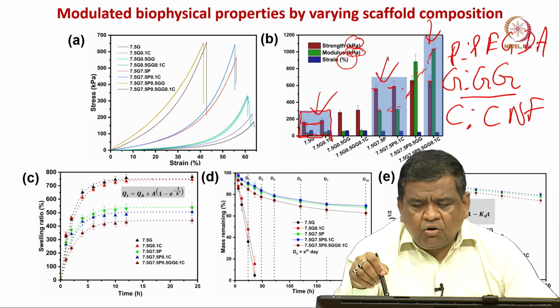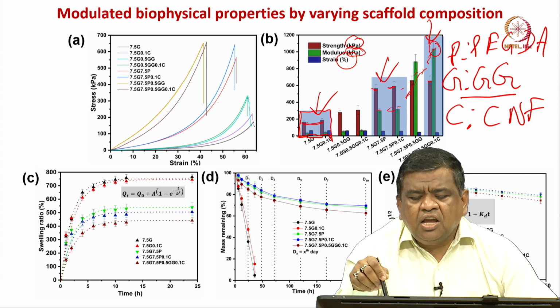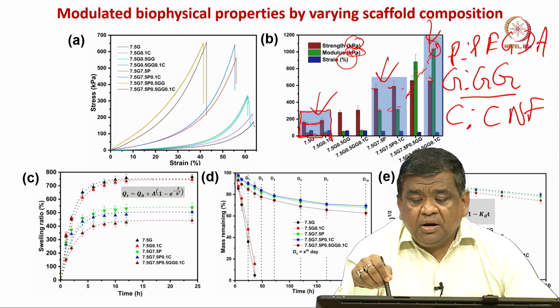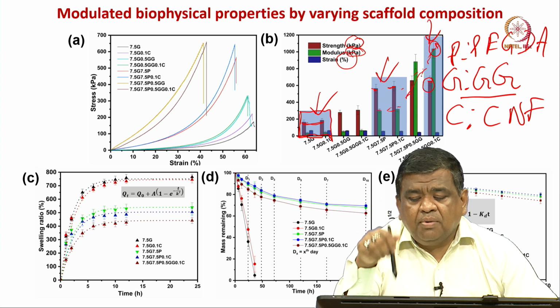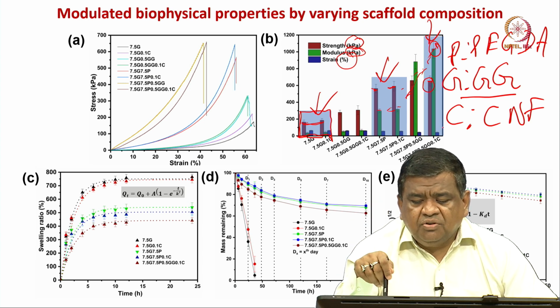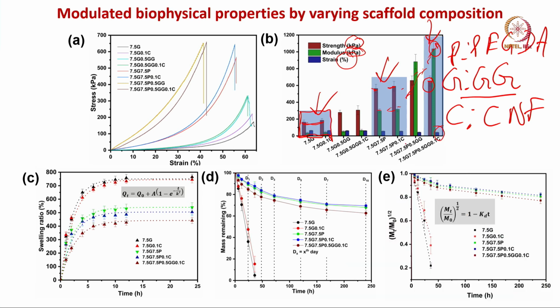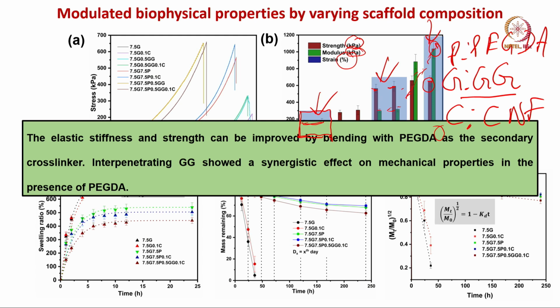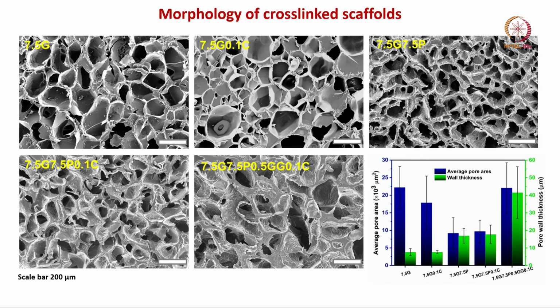So, you can get the combination of modulus almost like 1 megapascal, 1000 kilopascal, strength of almost 600 kilopascal, and there are differences, essentially strain to failure is reduced, right. So, the major message here: elastic stiffness and strength can be improved by blending with PEGDA as the secondary cross linker, and interpenetrating GG showed a synergistic effect on mechanical properties in the presence of PEGDA only.